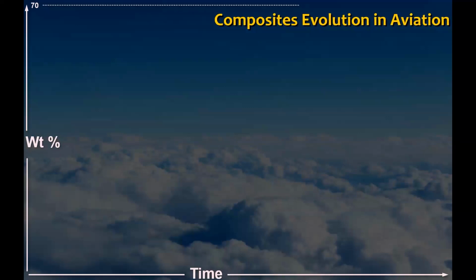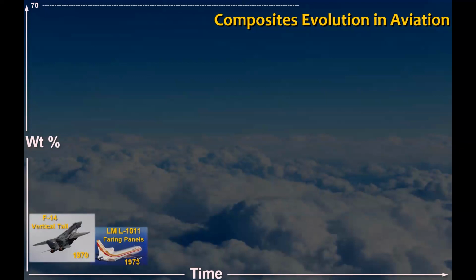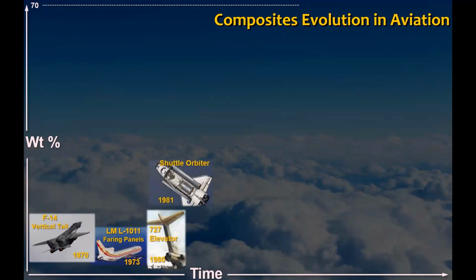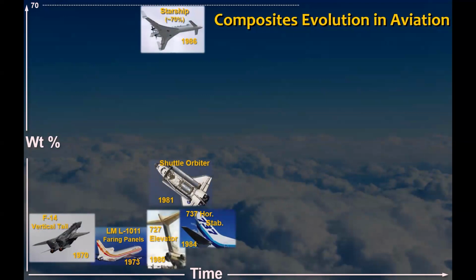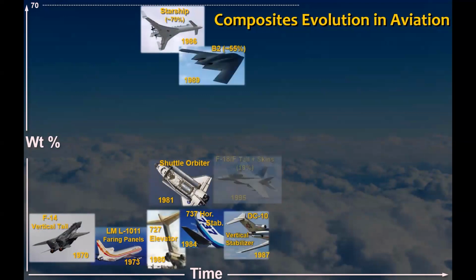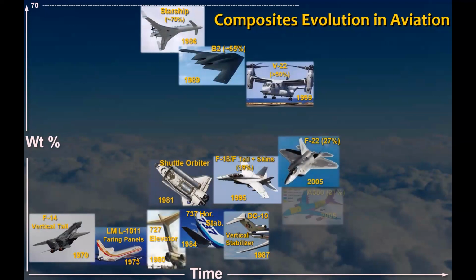Just hit the down arrows as you wander through this. I wanted to show you the evolution of putting composite materials, polymer matrix composites, into aviation applications. It has been a fairly slow journey, and it started with the F-14 vertical tail. If you keep pushing down, you'll see the pictures animating with time. The space shuttle orbiter here was only about 10% by weight, and look at all the airplane applications below it, in the 1, 2, 3, 4, 5% range.